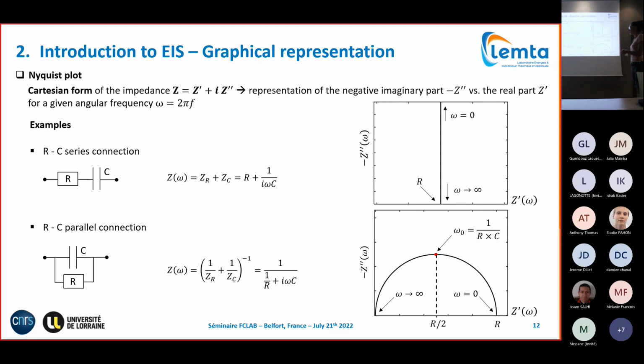If you have a parallel connection of a capacity and a resistor, then you will observe a half loop, a half circle in the Nyquist plot, with an intercept at low frequencies corresponding to your resistance and an intercept at zero at high frequency, and the highest point of this half loop corresponds to 1 over RC. So this shows you directly why this representation is convenient, because directly from the shape of your Nyquist plot, you can deduce a first estimation of your parameters.